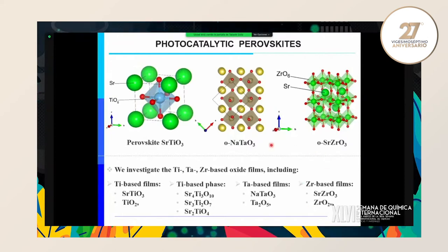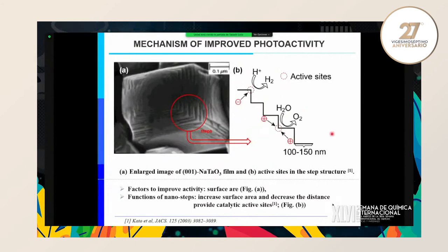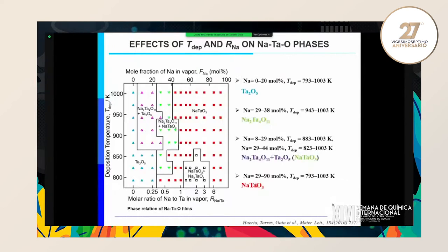And alkaline, in particular sodium compounds, are also very difficult because sodium is very reactive, forming nanoparticles in the gas phase. Sodium tantalate, strontium zirconate, strontium titanate, perovskites are very good candidates for photocatalytic material. Then we need very good material to study. And photocatalytic active sites could be steps or kinks. This is sodium tantalate powder. So we have to make very faceted sodium tantalate film or coating. So by choosing many conditions, we can find conditions to prepare sodium tantalate by changing temperature, gas sources, total pressure, etc.